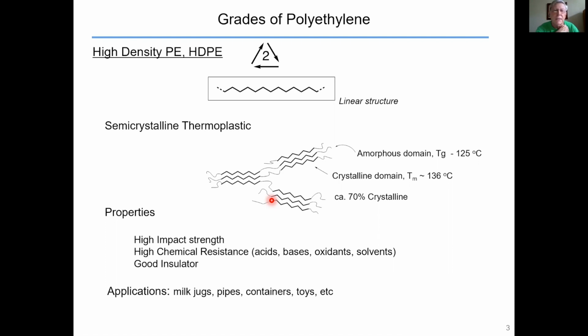That's high density polyethylene. Polyethylene is a semi-crystalline thermoplastic, and I'm sure those of you that have had a polymer course, this is going to be very simple, but maybe I should at least describe what that is. We have crystalline domains in the polymer. It's about 70% crystalline domains, and the Tm, the melting point of these domains, is around 136 for high density polyethylene. The crystalline domains are connected through amorphous material, and those amorphous materials have a glass transition temperature of about minus 125 C. So you've got an enormous workable range. Once you go below the Tg, the material becomes brittle, but between the Tg and the Tm, you've got a workable range, and you can see that's quite enormous.